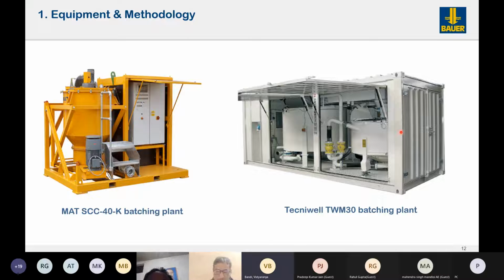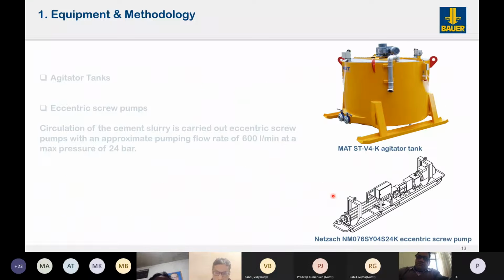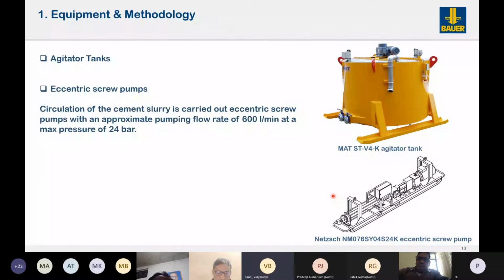Like this was a batching plant, wherein the cement and bentonite and plasticizer are mixed in and it is continuously agitated. Then this is another make, manufactured by Tecniwell. Then we have agitation tanks. When the cement, bentonite and plasticizer are mixed, the grout slurry has to be continuously kept in agitation so that it doesn't settle down and create a non-uniform slurry during the pumping.